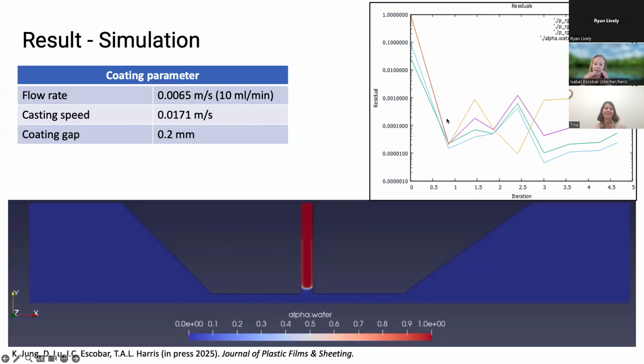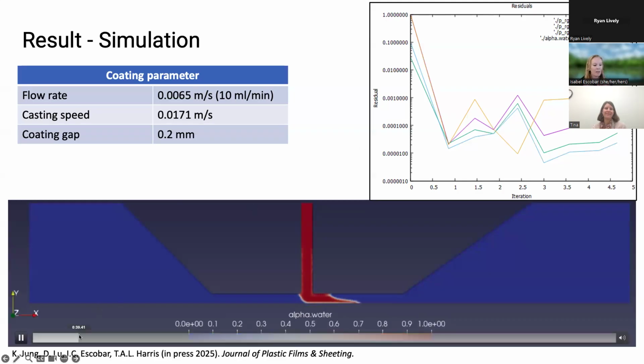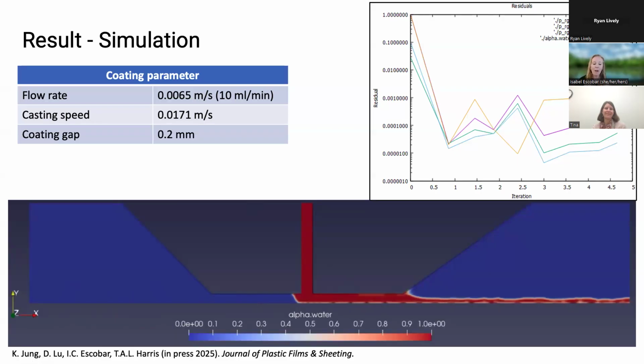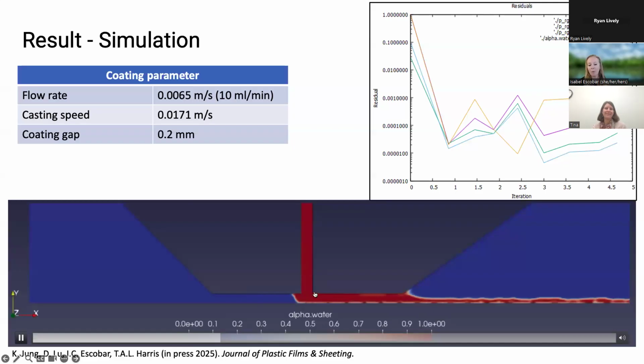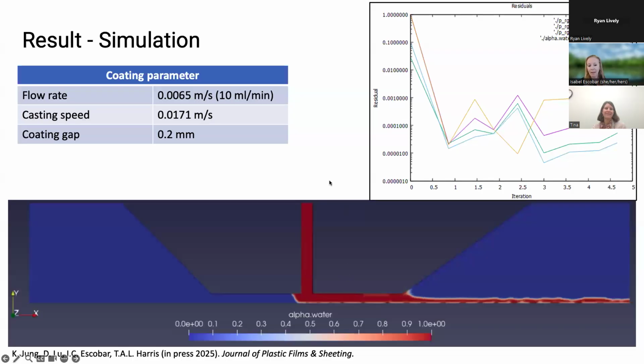The residual, we want it as tight as possible and as linear as possible during the simulation, because it means that those will be the perfect casting conditions. And if I move this here just a little bit, we can see that this case would lead to a perfect casting condition. The dope is moving at an appropriate flow rate over time. I'm not going to let the whole video play, but we don't have dripping in the back, and we're not moving so fast that this dope starts to have break lines here and significant air gaps.